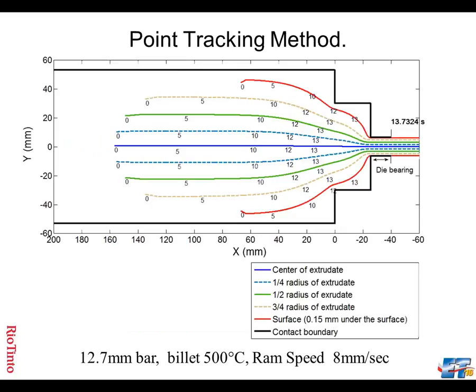We used a point tracking method, which is a rather neat way of measuring and predicting what the temperature is through the thickness of the profile and throughout the container. On the plot you'll see numbers, that is time. And you can see the metal is the red metal, for example, on the outside, the red flow path, which is the material going to the bearing. It runs a lot slower than it does through the center. This is in seconds.